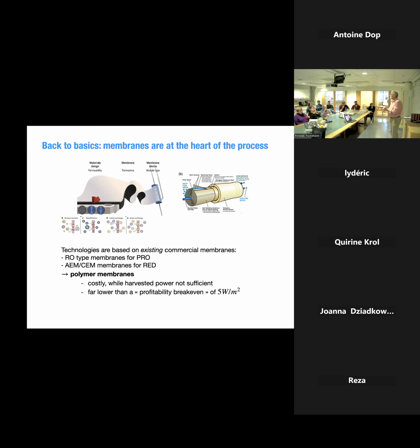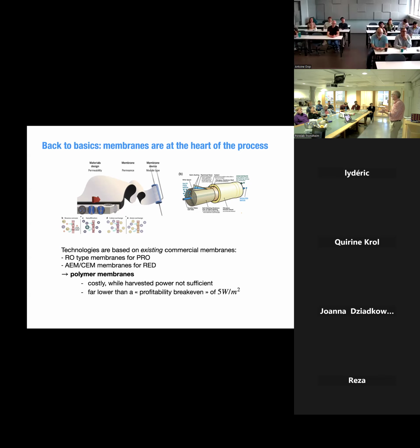And usually you do that by using a membrane which has a pore size in the range of angstroms. Of course, it's because the hydrated ion is 7 angstrom in size, so you need a very small size. So meaning you can make a simple estimate. Of course, you have a pressure which is huge because the osmotic pressure is 30 bars between seawater and freshwater, but the permeability is so small that you just kill the power.